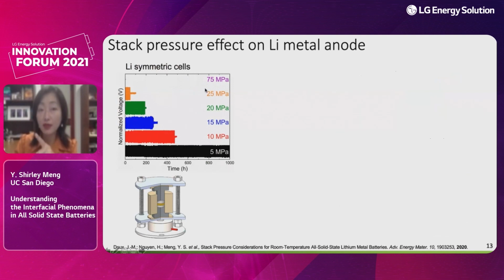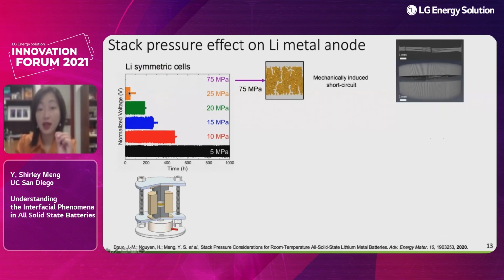But if you do it at a very high pressure, then the cell shorts, and it correlates so well with the amount of pressure—the higher the pressure you go, the quicker the cell will short. And to peek into the solid state batteries, it's very important that we have a tool that can allow us to look at a buried interface.